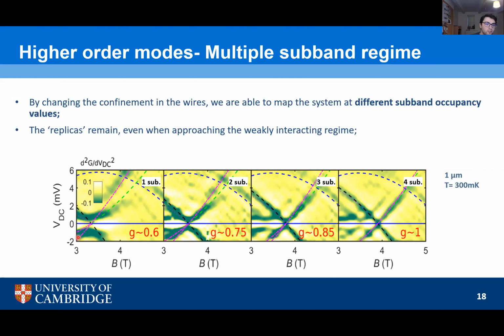Here, the magenta line is the extension. So you see spin charge separation here, and the magenta line is the extension of that towards positive bias, while the green dashed line is the extension of the spinon mode. What you see is that for 1 and 2 subbands, clearly two features are branching off away from the Fermi points, and they can be separately resolved. For 3 subbands, you can't separately resolve them, but there is some broadening there. Again, consistent with this replica, for this particular configuration, being too close to separate it from the spinon mode.